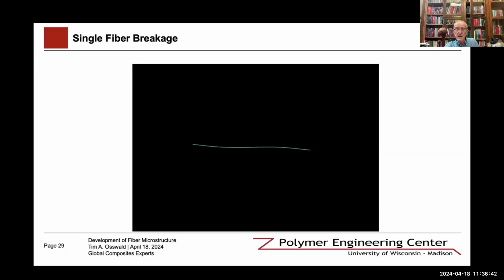So, for example, this is a fiber in shear, and we can introduce that into it. When we reach the radius of curvature, we break the fiber. Here we don't see the buckling effect, but rather the ends of the fibers get broken off. Again, the fiber continues on its Jeffery orbit. It deforms. It turns very slowly, and then as it moves out of the horizontal position, you can see failure. So this is, of course, simulated.